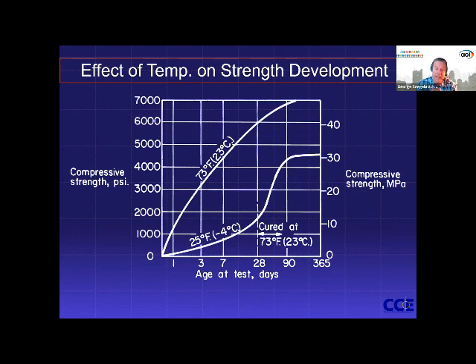If you neglected the curing and it's out in a cold environment here, 25 degrees F, and then reinstitute the curing later, no, you don't come back up to where you would have been, but concrete still rebounds nicely, and you still might be, hey, say if it was a 4,000 PSI spec, you would still achieve that goal. Yeah, like I said, it's not as high as you were had you done everything right the first time, but concrete, I just think it's very forgiving.